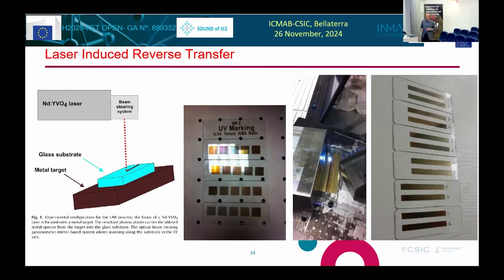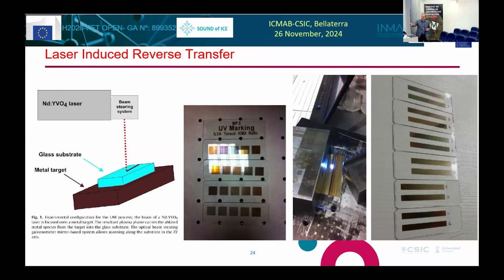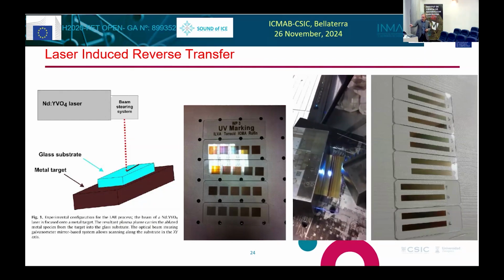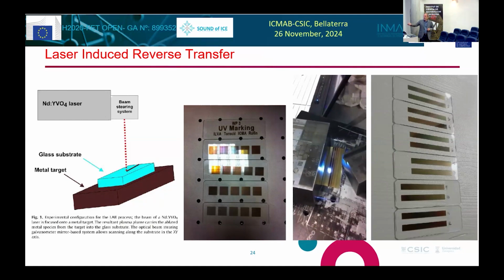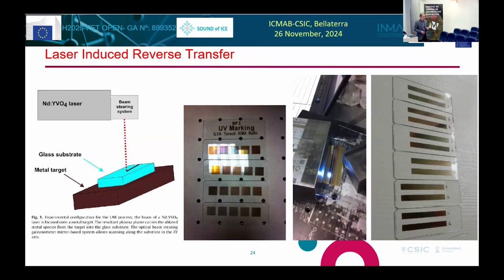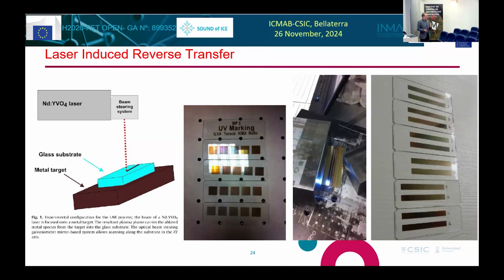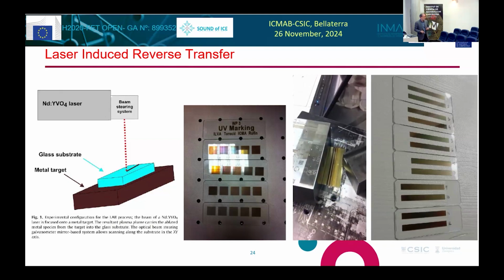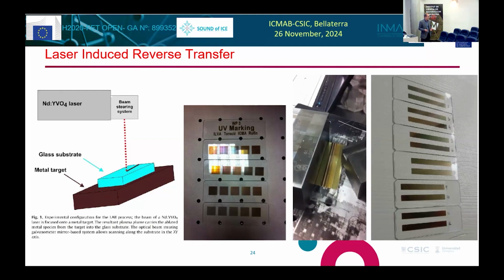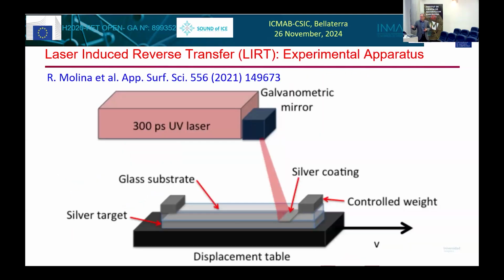So it's inside or outside. In this case, it's outside. This case is inside. Nanoparticles dispersed inside the glass, and this case is the metal on the surface. So you change the intensity of the laser, and you can selectively coat a glass with a conductive metal. And if you do that, this is another experiment that we did with the silver coating.